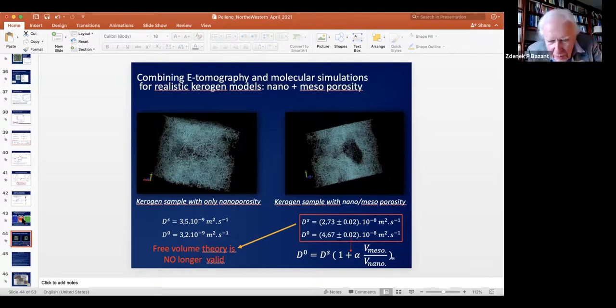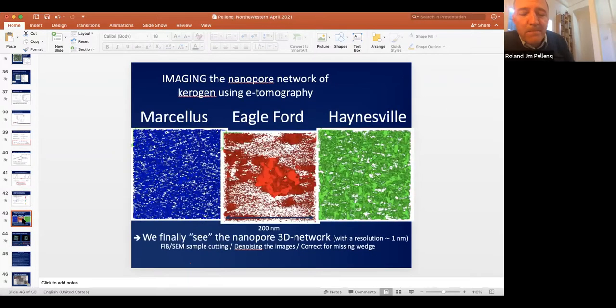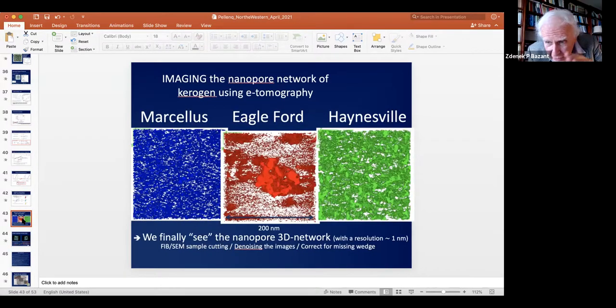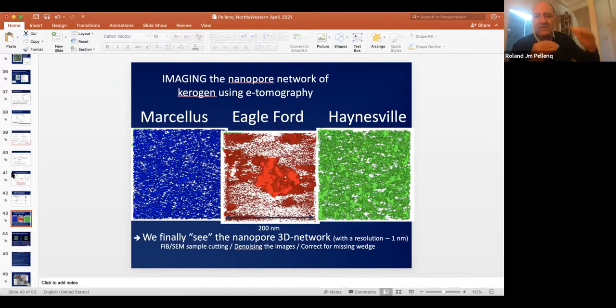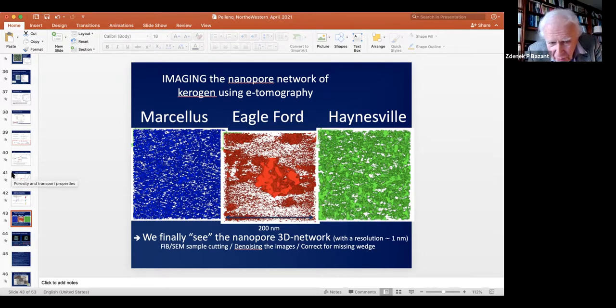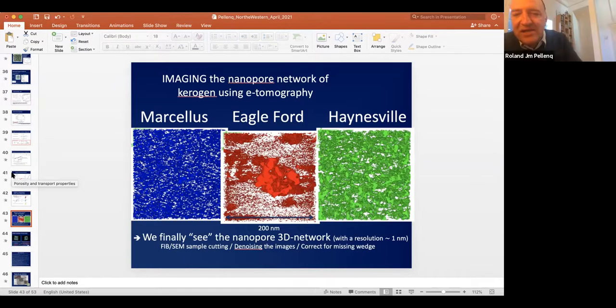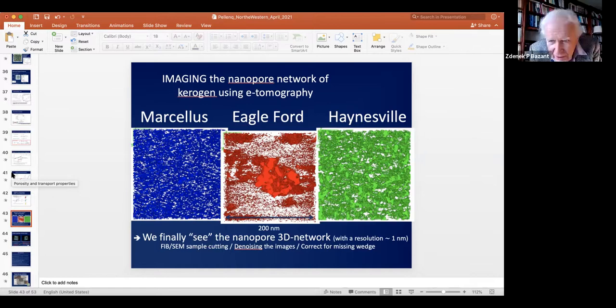By the way, Roland, the picture of the Marcellus shale. Yes. There was a horizontal cross section. No, I mean, this is right in the middle of the kerogen. So that's the way we actually extracted the sample. Yeah, but I suppose that in a vertical section there will be anisotropy. But that's not at the scale. The box size is actually 200 nanometers, so it's very small. My colleagues extracted a sample of the kerogen in a big, 50 micron nest of kerogen. So it's really at the core.